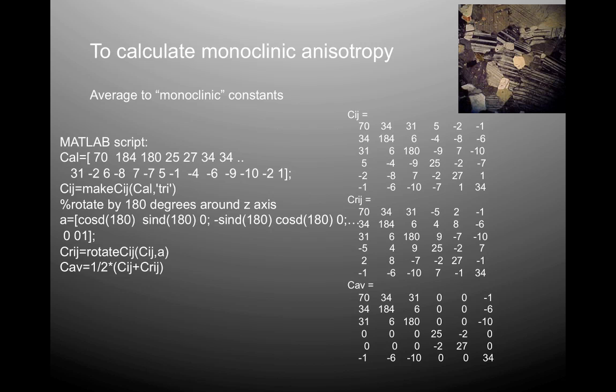There are a lot of zeros in there. Now, because of the way we've done this, we've formed an alternate version of monoclinic constants. If you remember in the past video, the non-zero monoclinic constants were in the 5th row and column. Here they're in the 6th row and column because of just how we've defined the rotations. They're still equivalently a monoclinic description of the material. So I label it monoclinic.